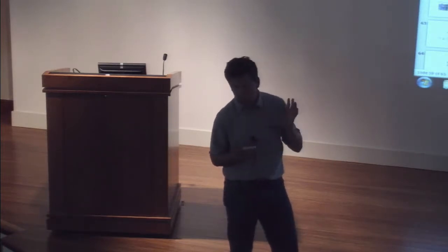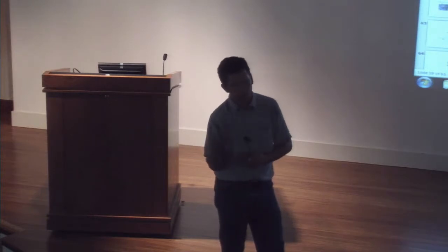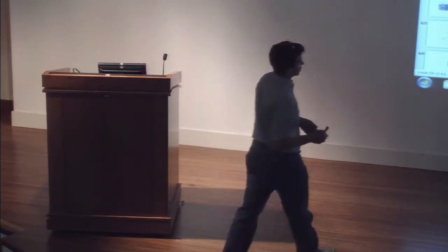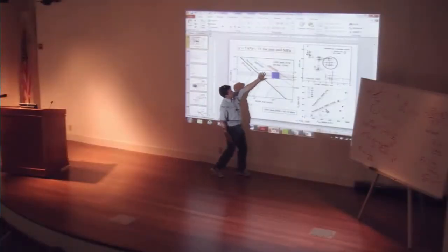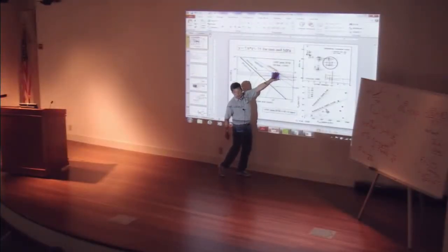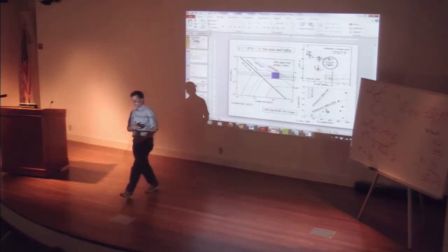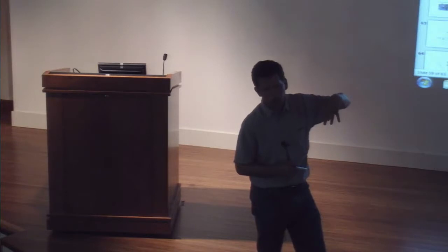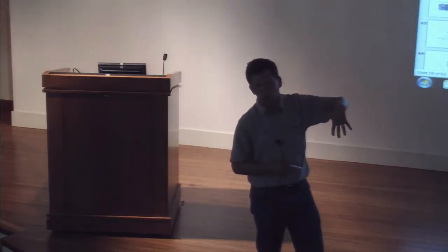One of the main things that people are worried about right now in trying to understand the rheology is that the diffusion creep field has this really strong grain size dependence. We need to understand where the grain size is in the mantle, and that piezometer relationship over here, for this high temperature, plots well into the dislocation creep field. But one of the things you can do with this type of diagram is change the temperature to a much lower temperature, and you'll find that the recrystallization line moves into the diffusion creep field.